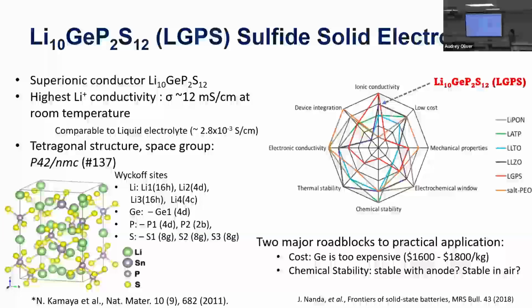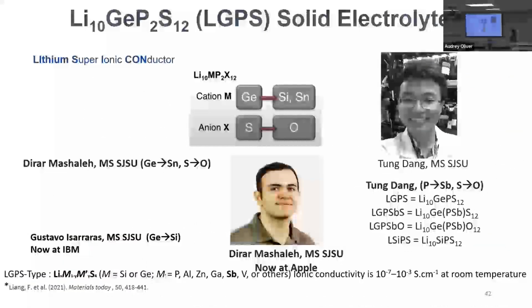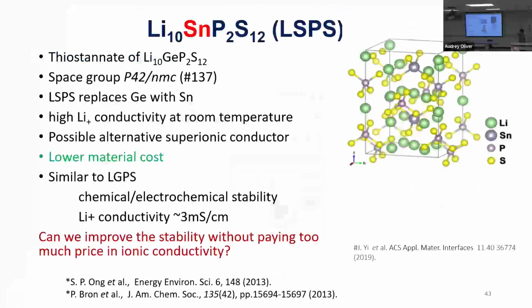And then sulfur, usually sulfides are not very stable. Oxides are more stable than sulfides. So we replace sulfur with oxygen, with different compositions. We also look into other properties, such as mechanical properties. This was done by my master's students at San Jose State. Germanium replaced with silicon and tin, which are cheaper, and sulfur with oxygen. And also with different compositions. We also replaced phosphorus with antimony.